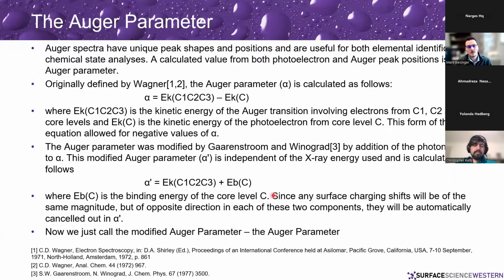I won't go through this very much, but if you take the peak maximum of the Auger peak and use its kinetic energy, you add that to the binding energy of your core photoelectron peak, you get what's called the modified Auger parameter.